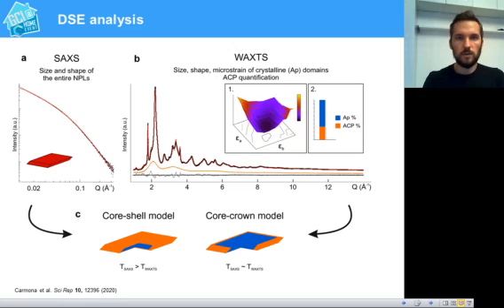Allocating the amorphous and the crystalline phases within the nanoplates can be done with two different models. One, a core shell model, where the amorphous material is distributed along the surface of the crystals, or a core crown model for which the amorphous phase is mainly allocated on the width and length of the plates. And the latter is the model that better fits our data.